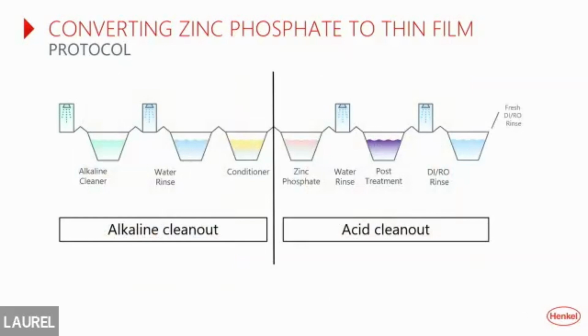And for the actual cleanout, it's done by the system. The first half of the system, in both zinc phosphate and zirconium, is usually alkaline, because we've got our alkaline cleaners. In the case of zinc phosphate, the water rinses and the conditioner are alkaline. Starting with the zinc phosphate stage, everything after that is acidic. So for the boil out, when we do a conversion, we alkaline boil out the cleaner stages, and we acid boil out the subsequent stages. And zinc phosphate and the water rinse after, those 2 stages are usually the dirtiest.